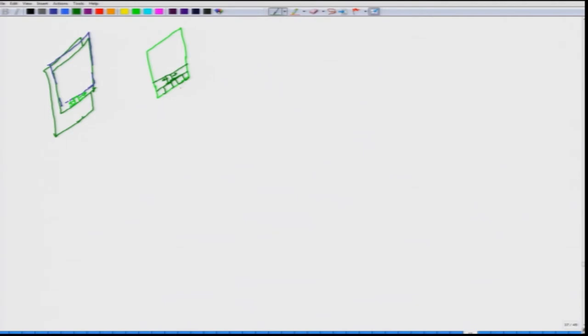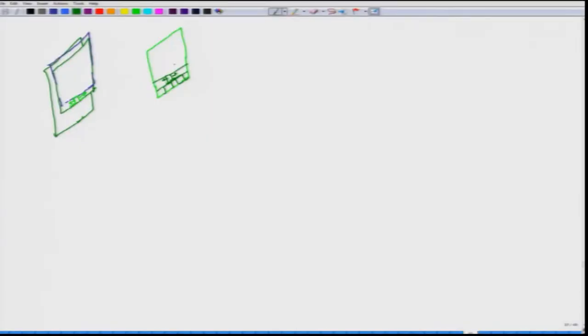We are not even talking about one whole slip plane moving simultaneously - only a small jog or a small step in it is actually getting formed, and that then spreads apart to allow the dislocation line to move. And again, if you remember from our discussion for glide where kinks were formed, this need not be just one step at a time. There will be jogs at some places which will keep moving up, and there will be some side dislocations whose character we will see in a moment, and they will keep moving on the other sides.